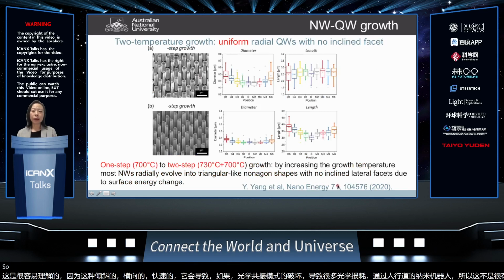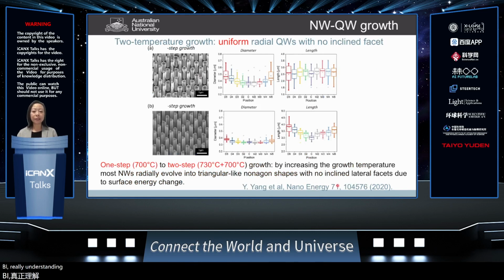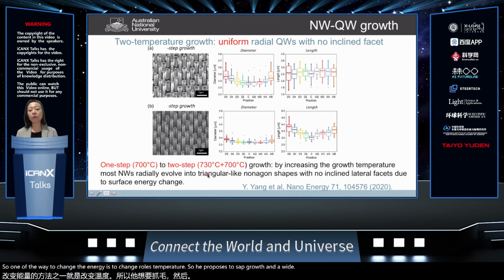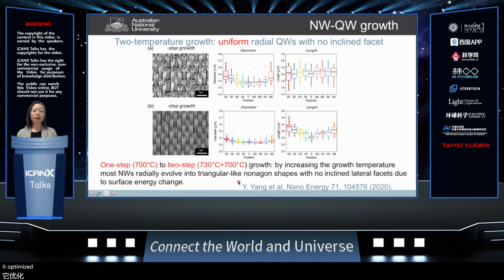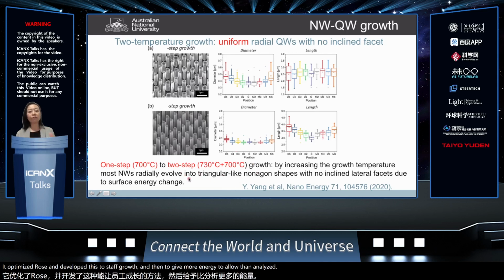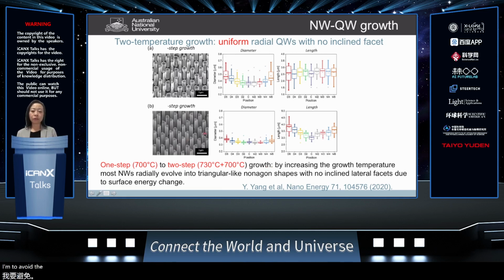So In-Suk, again, by understanding that the growth is really highly related to surface energy, and that one of the ways to change the energy is to change the growth temperature, he proposed a two-step nanowire growth, instead of using only one temperature growth as we had before. He optimized the growth and developed this two-step growth to give more energy to allow the nanowires to radially evolve into a triangular shape, rather than all these different types of shapes. And he's able to demonstrate a much nicer morphology with no inclined facet anymore, due to the surface energy change.